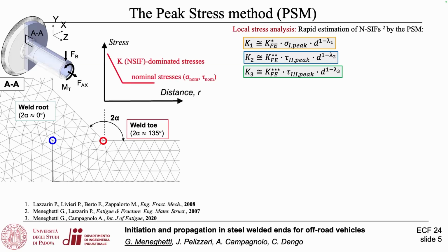We have demonstrated that in the K-dominated zone, if you take the maximum principal stress, for example, at the weld toe, and you insert it in this formula, you can estimate the notch stress intensity factor. So sigma 1 peak is the maximum principal stress at the weld toe. d is the average value of the size of the finite element that you use. 1 minus lambda 1 is the stress singularity exponent, and K* FE is a well-known constant based on the type of finite element adopted.